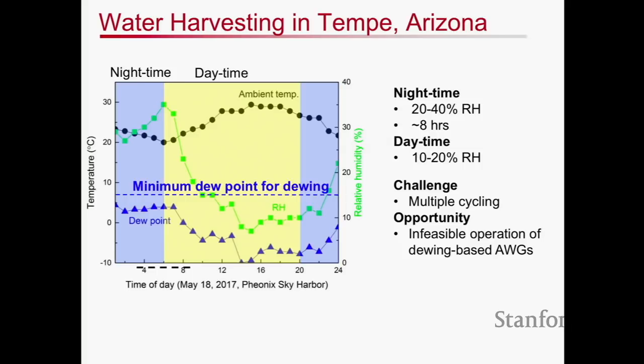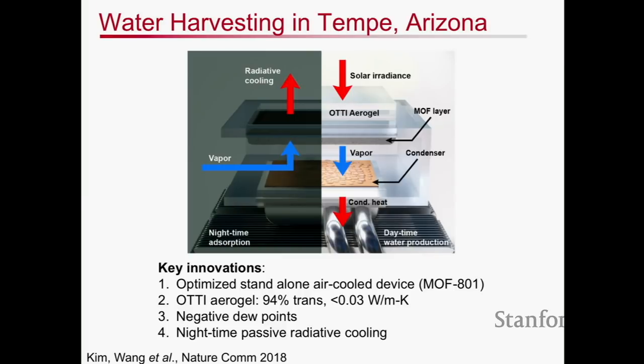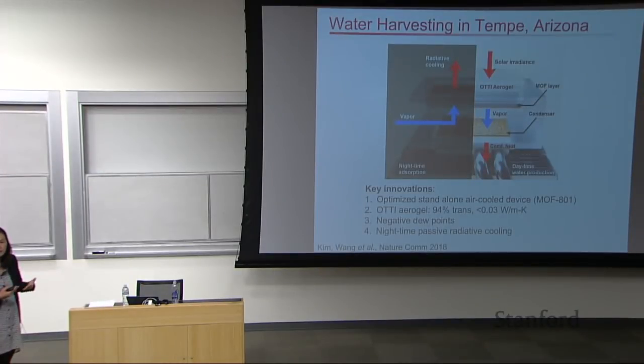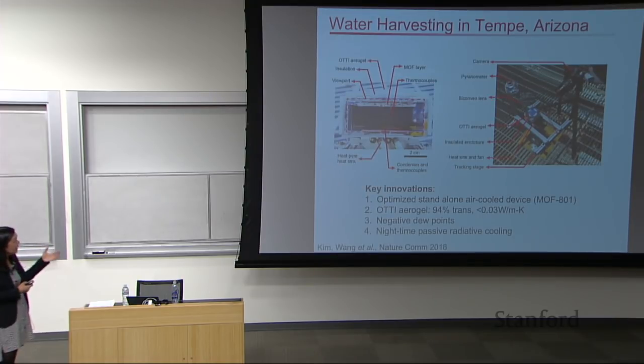What we've been working on is an optimization of that process I showed you earlier, with a few improvements. One is to further capture the heat from the sunlight itself by incorporating that same aerogel that we fabricated earlier, to better insulate but still allow for great solar transmission, right? And then also using an air-cooled design instead of a thermoelectric cooler, and a few other things that I won't get into in detail, to further demonstrate the promise of this technology and actually take it to this Arizona condition where the humidity is low, right? This is the opportunity space that we found.